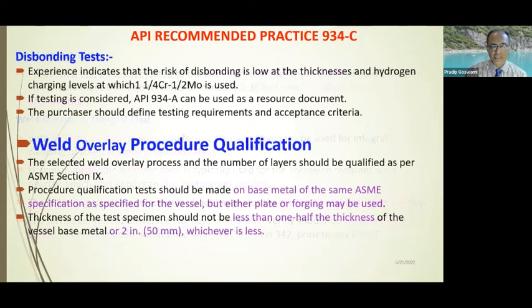And disbonding test, like 934A. Disbonding test is not a requirement because experience indicated the risk of disbonding for these vessels at this thickness and the hydrogen charging levels are low. But if the client wants the disbonding test to be done, then API 934A can be used as a resource document.